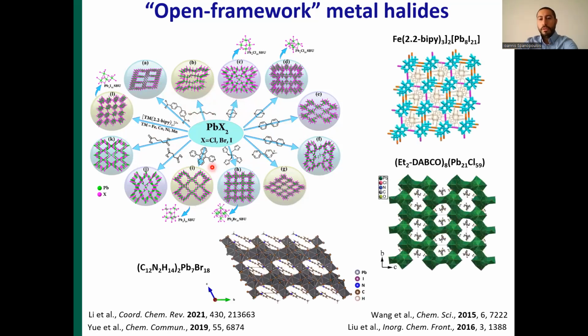Although these compounds look porous, in reality the organic countercations, the templates that give rise to these beautiful 3D architectures, reside in the cavities of the material and cannot be removed without structural collapse, because they work not only as a templating agent, but also as a countercation. And all these different types of compounds, despite their beautiful 3D porous network, due to the presence of these organic countercations, have no accessibility in this porous network. Gas sorption studies are absent, deriving exactly from this limited access to the pore network.